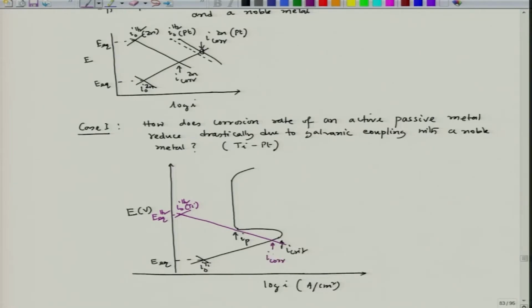So, this becomes i corr titanium. That means if we leave a titanium piece in an electrolyte containing hydrogen ion, say acid, where hydrogen evolution reaction is the cathodic reaction, due to mutual polarization of titanium and hydrogen, both will try to drag the potential towards the mixed potential. This is the mixed potential, E mix, and titanium has got a lower equilibrium potential than hydrogen. So that is why the corrosion rate is falling in the active zone of the anodic polarization side of titanium.